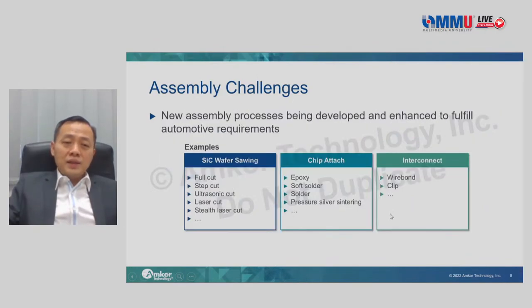But what comes after that in the semiconductor with this material change is an entirely new set of requirements in the assembly process, right? Some of the new assembly processes need to be developed from zero, and some need to be enhanced. For example, with silicon carbide wafer sawing, we have the conventional full cut and step cut, but now we have to venture into ultrasonic cutting, laser cutting, stealth laser cutting, and so on and so forth, right? And this portion is still under very aggressive development. And for better attaching the chip in the package, the conventional epoxy or soft solder or even solder print may not be sufficient. We have to go into a new die attach material called pressure silver sintering.